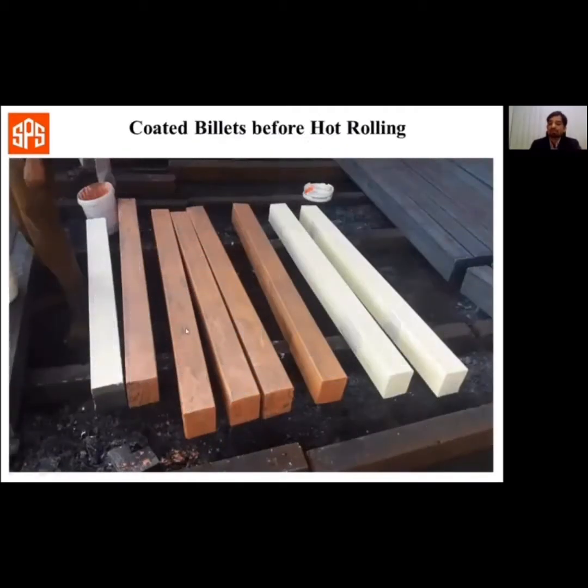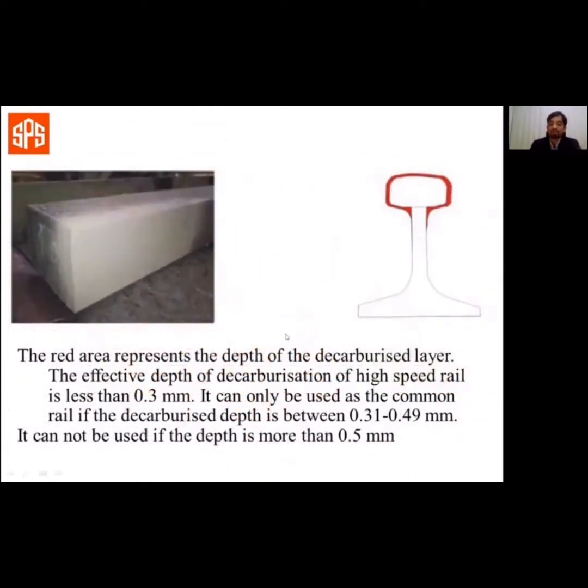These are billets coated before hot rolling to control scaling and decarburization. In the hot rolling of rail steel, the part that comes in direct contact with the locomotive is of utmost importance. Here, decarburization needs to be controlled to bare minimum. If not, it could lead to rail breakage, risking lives of passengers in the train. You can see that coating is sprayed only on the side that comes in contact with the locomotive.